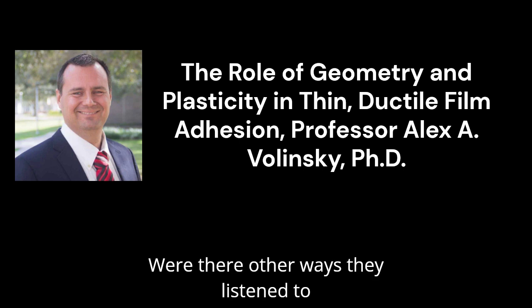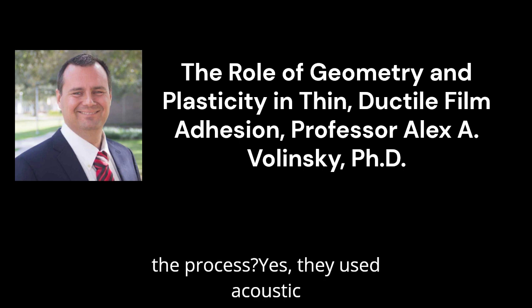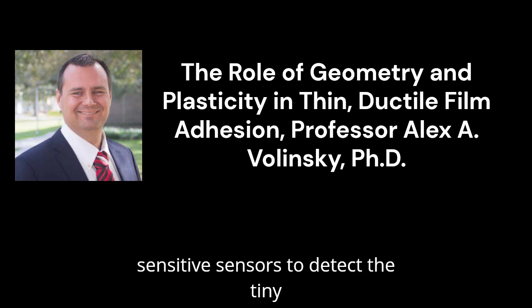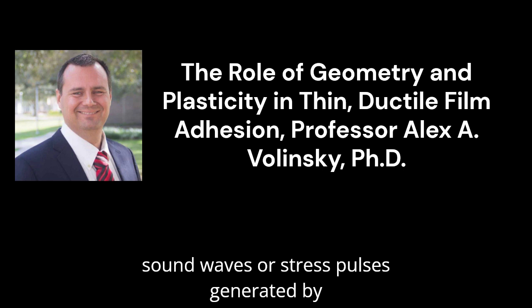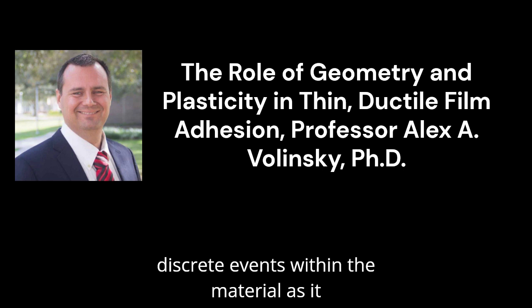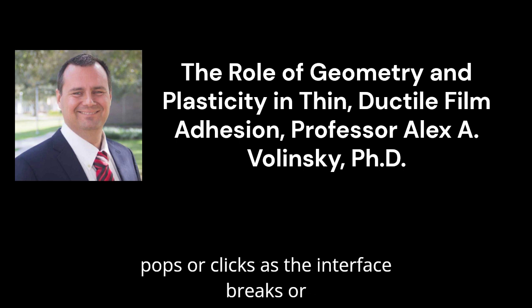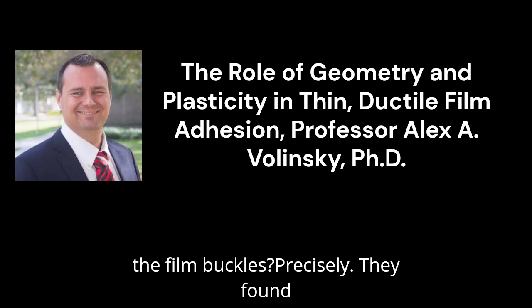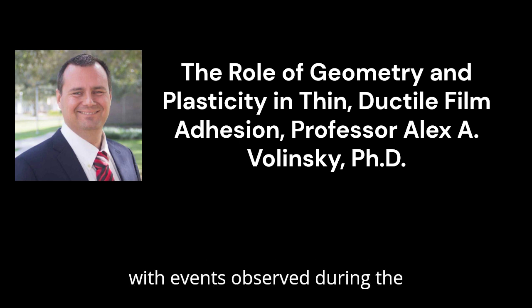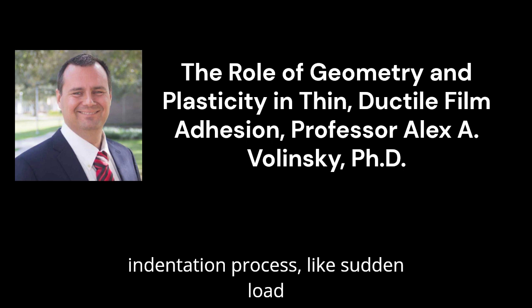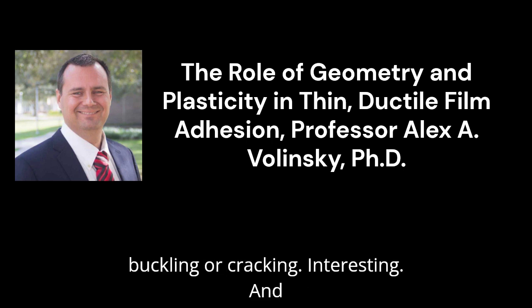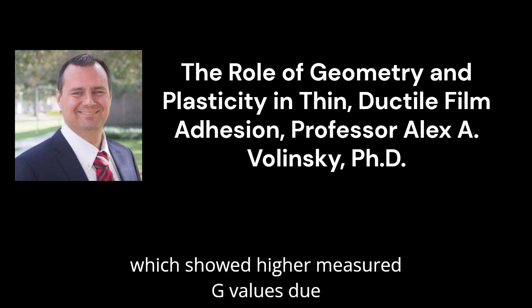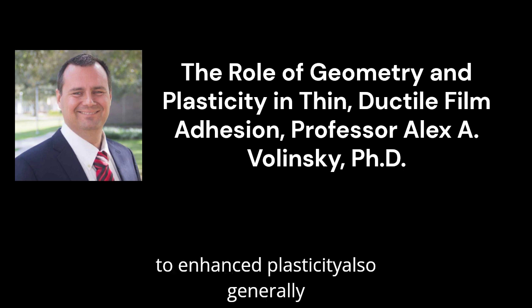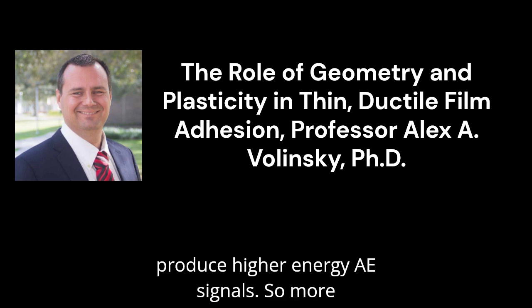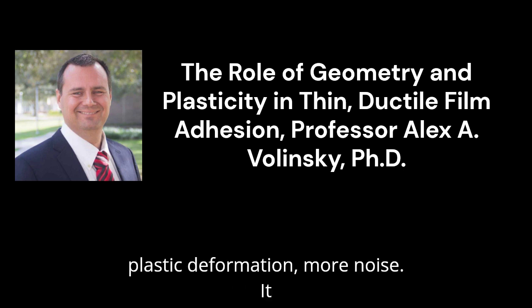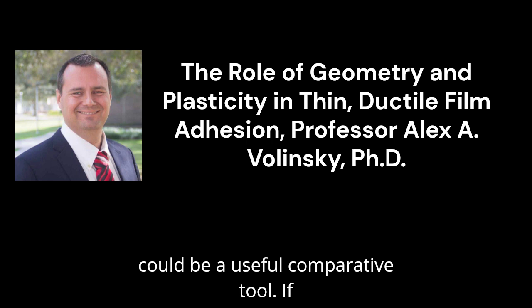Were there other ways they listened to the process? Yes, they used acoustic emission, or AE. This involves using sensitive sensors to detect the tiny sound waves or stress pulses generated by discrete events within the material as it deforms or fractures. Like listening for pops or clicks as the interface breaks or the film buckles. Precisely. They found that these AE signals correlated well with events observed during the indentation process, like sudden load drops, which are often associated with buckling or cracking. Interesting. And samples with the titanium underlayer, which showed higher measured G values due to enhanced plasticity, also generally produced higher energy AE signals. So more plastic deformation, more noise. It suggests that, yes, this implies AE could be a useful comparative tool.